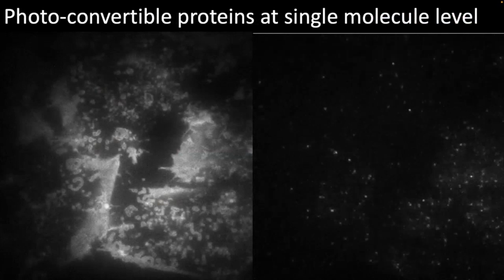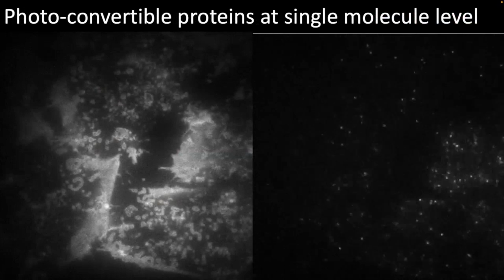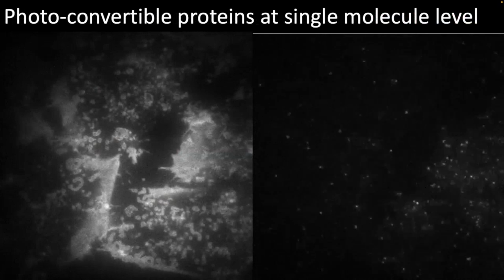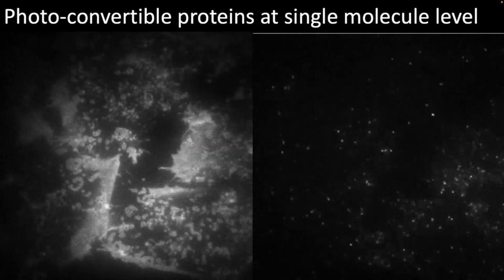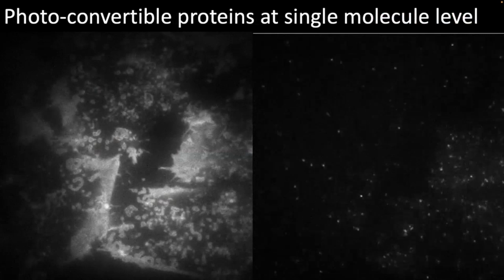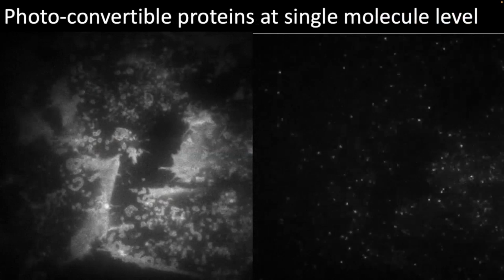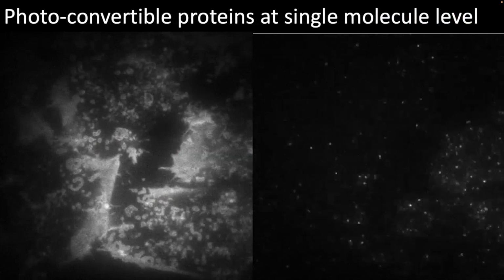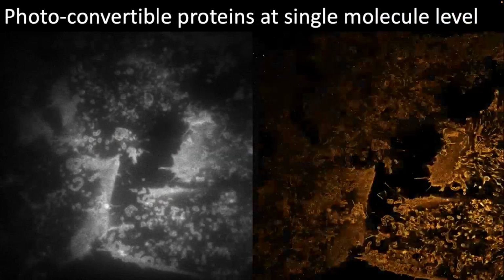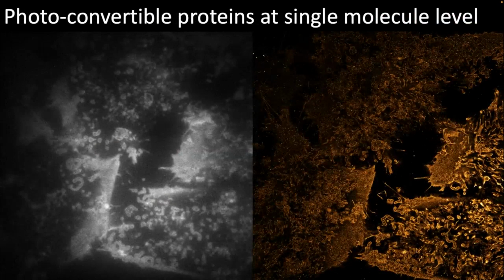If you then go through your movie, and for every frame, you fit these dots with a 2D Gaussian, then you know the exact position of every molecule. And then you reconstruct the image, so you plot every position that you acquired during the movie. Usually we do 5,000 frames, so it takes around 4 minutes to acquire this data. Then you get images like this. And you can see that even though from the single dots you are not able to discriminate the structure, if you acquire enough single molecules, you can get the same image as the diffraction limited one, but of course with an improved resolution.